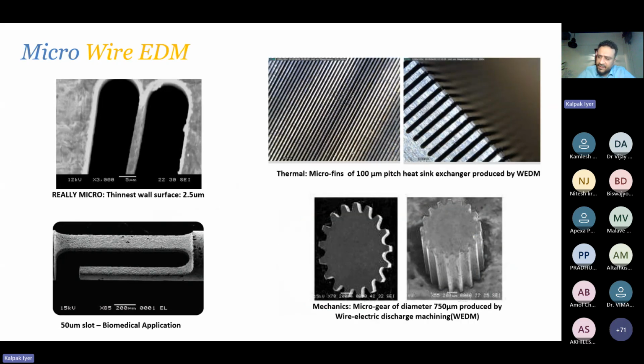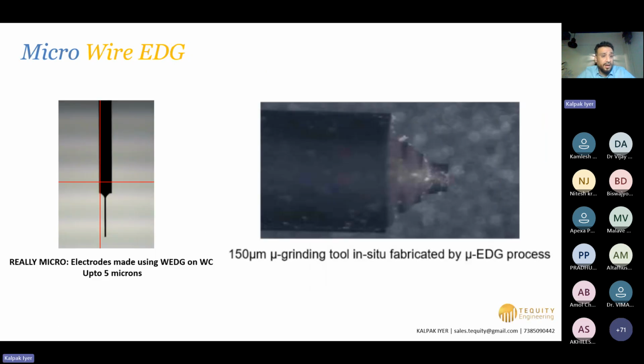Similarly, micro wire EDM, we all know what wire EDM is. So micro wire EDM usually uses very fine wires. If I remember correctly, 20 microns is the smallest wire that we use. I might be wrong. It's maybe 30 microns. Maybe 20 or 30 microns. Here you can see two slots, and the wall between the slots is 2.5 microns. It's very small. Again, this is through wire EDM, and some micro fins made, micro gears made, so micro wire EDM. Wire EDG, which I told you during the micro turning example.